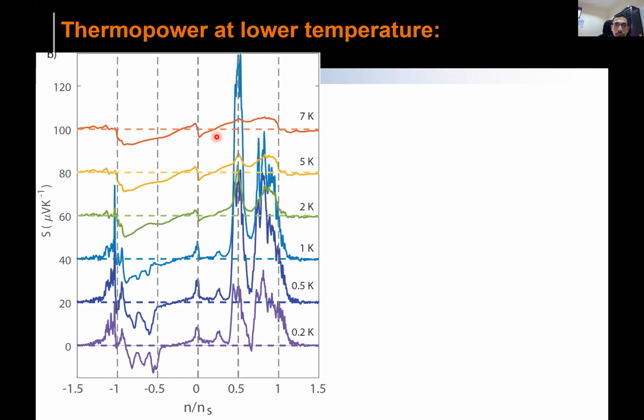So you see, this is the curve. This is the main heart of the main result here. What I was trying to show: you see now at 7 Kelvin, again, almost there is a similar structure, but near this half filling, remember, half filling with 2 electrons per Moiré unit cell. That I'm calling a half filling. Because these nomenclatures are different in different papers and textbooks.